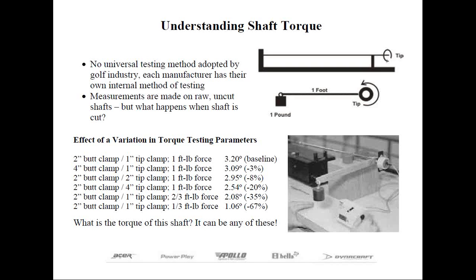A few years ago, we were designing one of our house brand graphite shafts using an existing model. We substituted two longitudinal layers — which control the flex of the shaft — for two layers of bias ply material to reduce the torque, and also substituted some higher modulus material — a fancy term for high strength — to compensate for the change in stiffness via fiber orientation. When we looked closely at these two models, the weight, flex, and geometry were identical. The only change was the torque and added material layers, which completely changed the trajectory.